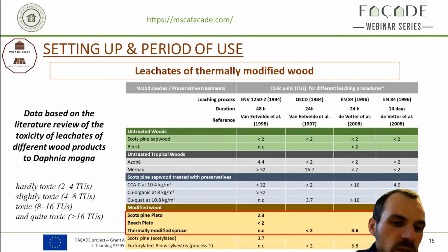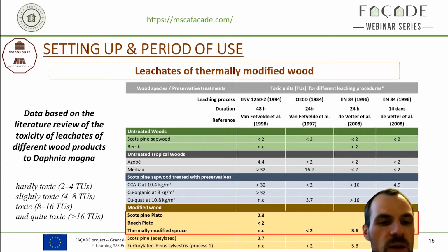For example, toxic units ranging from 2 to 4 concern hardly toxic materials, whereas toxic units higher than 16 are quite toxic. We can see on this table that Scots pine and beech treated by the Plato process have toxic units lower than 2. Whereas if you look at untreated tropical wood or CCA treated wood, we have a toxic value higher than 30. So we can see that thermally modified wood leachate has a lower toxicity value than other tropical or chemically modified wood.